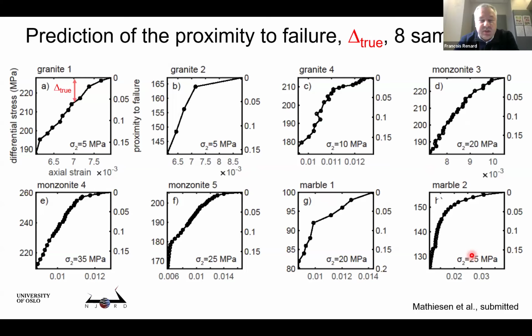So we started with 8 experiments. That's the same 8 as before. That's a stress strain curve, so the shortening of the sample as a function of the loading. And the last point here on the right side of each plot is when the sample is failing. So during all this increase of stress, the sample is accumulating damage until it fails.